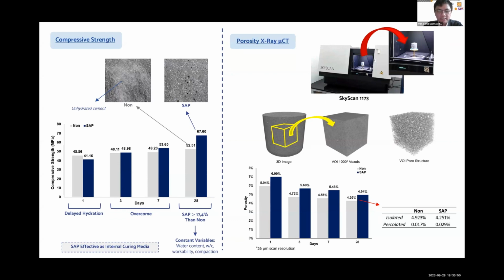Additionally, this study uncovered the phenomenon of delayed hydration at day 1 to day 3, as evident by the compressive strength between days 1 and 3, which has yet to be explored in previous studies. Porosity of the specimen can be obtained from X-ray micro-CT from the 3D image. A volume of interest of 1000 voxels was chosen on the pore structure and porosity obtained from thresholding.